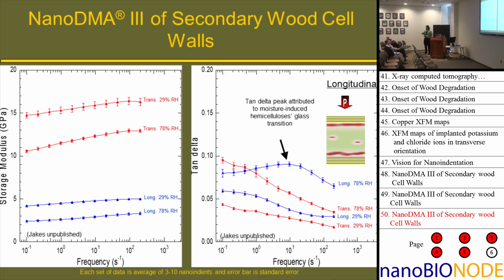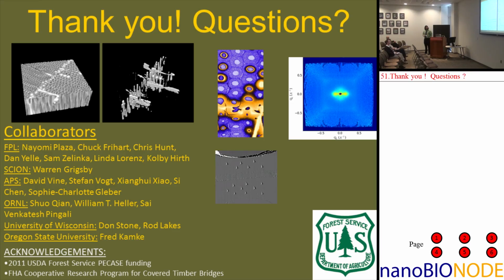And so this is another tool that we can use: if you want to develop a wood treatment that prevents fungal decay, we believe that you have to target the hemicelluloses to prevent the glass transition, to prevent the ion diffusion, because the initial stages of fungal decay require ionic diffusion in the wood cell wall to do some non-enzymatic degradation, because there's not enough room in the cell wall for an enzyme to get in there to begin with.